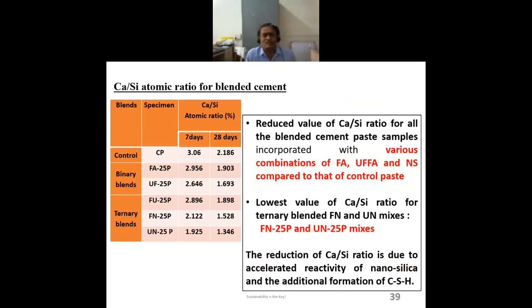So let us see what the Ca/Si ratio for all the mixes talks about. Now you can see here, for the control, the Ca/Si ratio for 7 days is 3.06, and for the ternary blend with nanoparticles it is 1.925. Even for the binary blend, it was around 2.9. At 28 days, it is almost half, 2.18, and the moment you go here, it comes to around 1.3. It means most of the calcium hydroxide is consumed, and that is nothing but the pozzolanic reactivity.